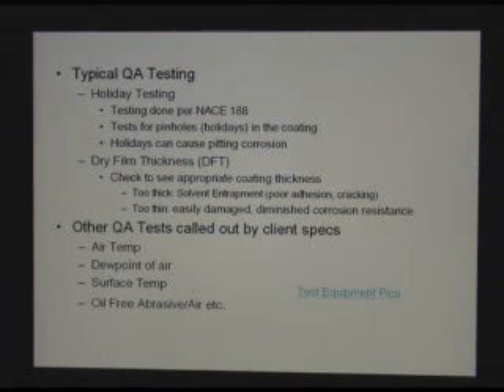Here are the testing requirements. There are many more than this, but here are some typicals. Typical is holiday testing, where we test the surface for any pinholes and imperfections. It's an electrical resistance test. We test for the dry film thickness, which is the thickness of the film after it has dried, of course. And then the other tests like air temperature, dew point of air, surface temperature, ambient temperature. We test to make sure that the air used for blasting is oil-free. We also test adhesion once in a while or other items.